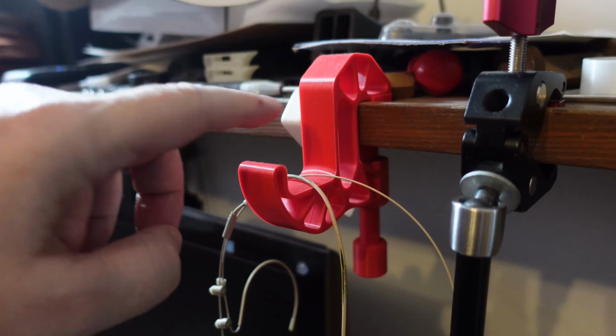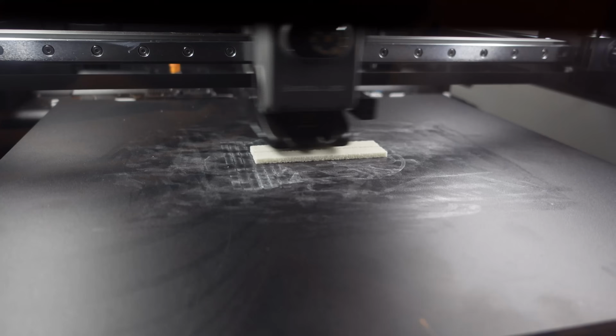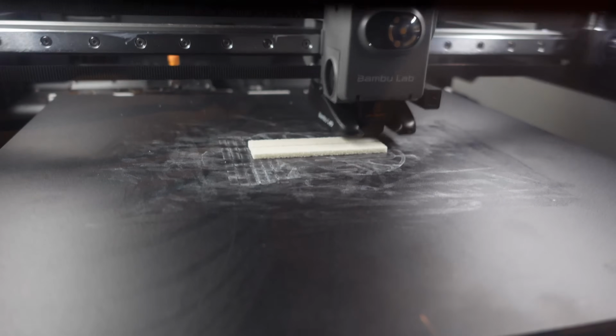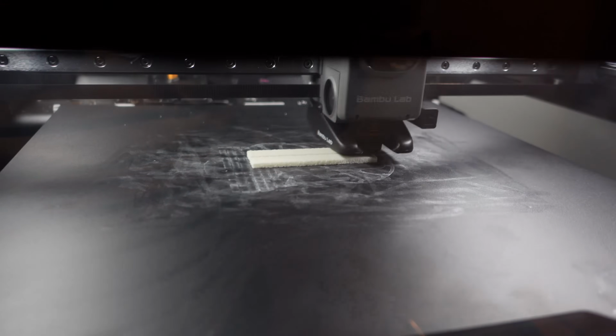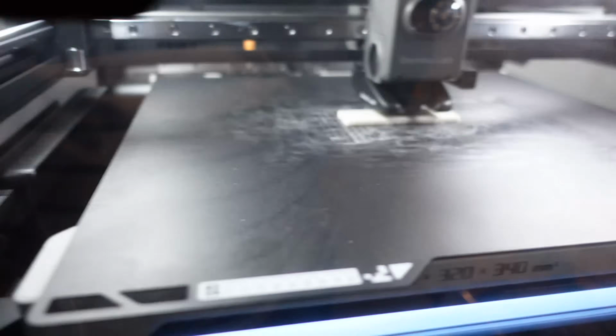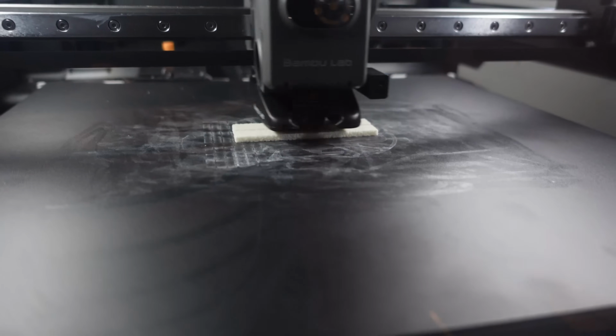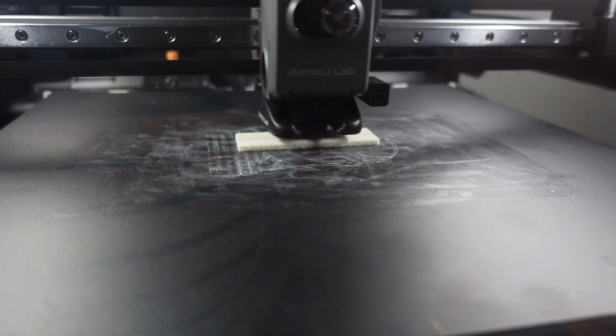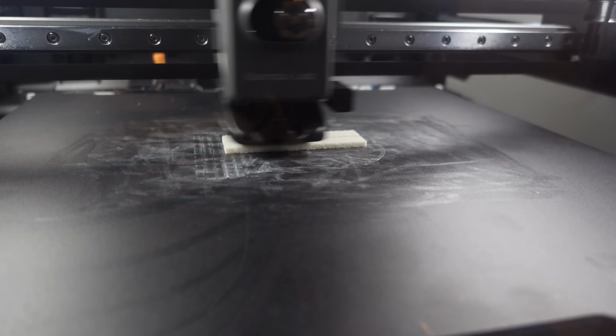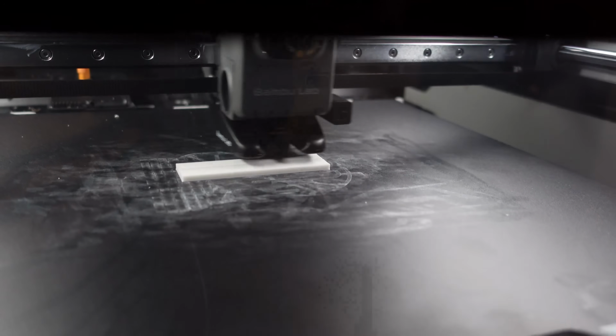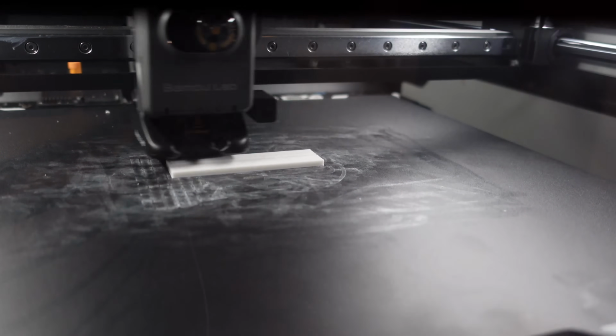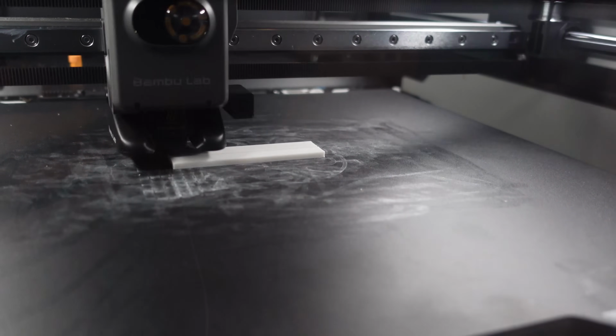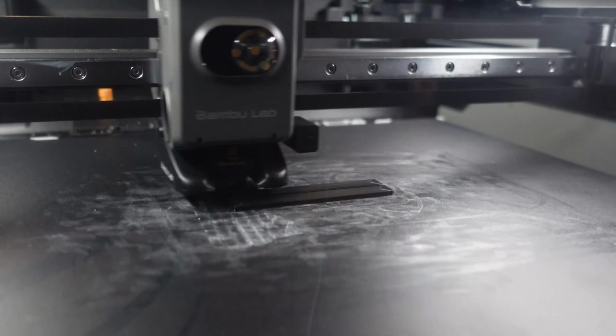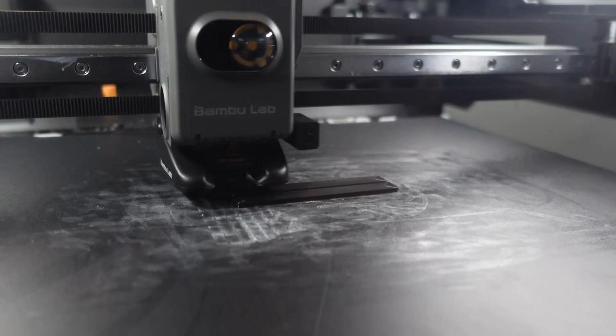Something like this. I want to print a few more test objects for the bending test, to test it with my new tensile testing machine. And this ABS-GF was here in open air for 1 week, and it already absorbed some moisture. I have the same test objects like before the drying. Same test objects from polycarbonate even after 1 week are completely fine. I can already see that PC ABS will be fine too.